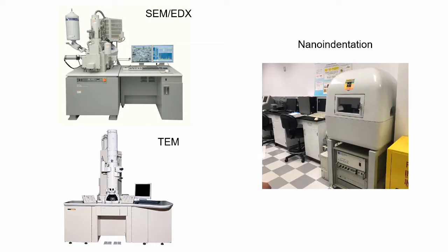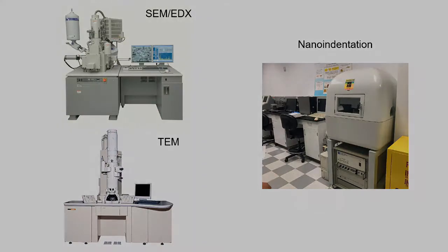The two samples we received from NASA differed in their ratios of holey graphene to palladium-doped holey graphene. The ratios are 1:1 and 1:5 respectively. Using scanning electron microscopy, energy dispersive X-ray spectroscopy, and transmission electron microscopy, we studied the nano and micro scale morphologies of these powders. Due to the limited quantities of doped holey graphene and the destructive nature of nanoindentation testing, we used holey graphene films pressed at 3.6 and 9 metric tons to obtain the mechanical properties.